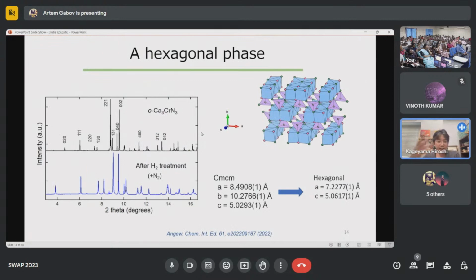But after the catalytic activity test, we examined the sample with X-ray diffraction, and found that this material's crystal structure has changed. Before this catalysis test, the crystal structure is orthorhombic with these lattice parameters. But after reaction, the X-ray diffraction pattern can be indexed with a hexagonal pattern with an a-axis of 7 angstrom and a c-axis of 5 angstrom. Okay, so the crystal structure has changed. But in contrast to the examples I showed for topochemical reactions, we couldn't rationalize these crystal structural changes.